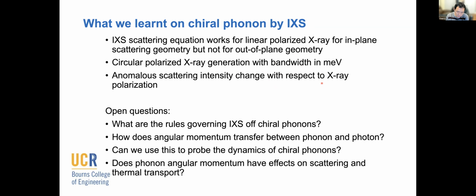But we actually open more questions than we solved, because now the questions are, what is the right rule to calculate inelastic scattering intensity, and how does angular momentum transfer between phonon and photons in this process, or what selection rules are there in this process? And if those two problems are answered, we should be able to use this as a probe to probe the chiral phonon dynamics, and maybe further to understand the questions of whether those phonons have special properties that can affect their thermal transport process. Okay, that's all I have today, and thank you.